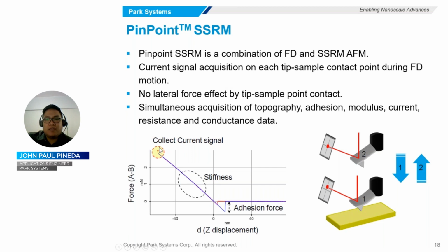So here, the electrical data is acquired by measuring the current flow produced by the application of a biased voltage between the conductive tip and sample at each landing point. Unlike conventional SSRM, the lateral force effect from tip to sample contact is eliminated in this technique. In addition, this technique can provide topography, mechanical, and electrical data at the same time.